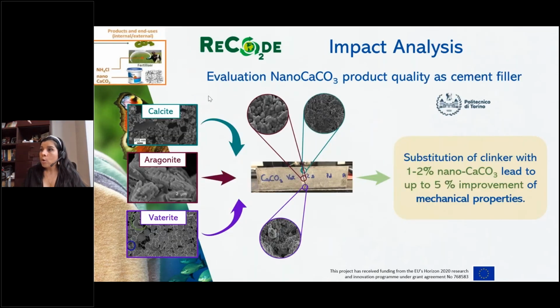Then we are also evaluating the impact of these products in the final cement plant product, that is the concrete, and we have already proved that by substituting the clinker with 1 to 2% of our nano calcium carbonate particles, it was possible to achieve up to a 5% improvement of the mechanical properties of the concrete.